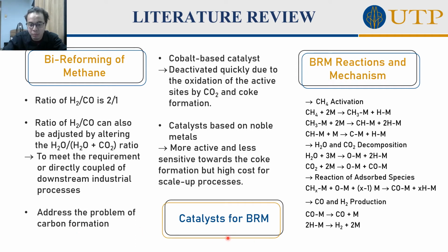For the catalyst for bi-reforming, previously, researchers utilized cobalt-based catalyst for the reaction, and it deactivated quickly due to the oxidation of active sites by CO2 and coke formation. The next one is catalyst based on noble metal, which is more active and less sensitive to coke formation, but it is high cost for scale-up processes. This is the bi-reforming reactions and mechanism, which consists of four paths: the first one is CH4 activation, then H2O and CO2 decomposition, reaction of intermediates, and last but not least, CO and H2 production.